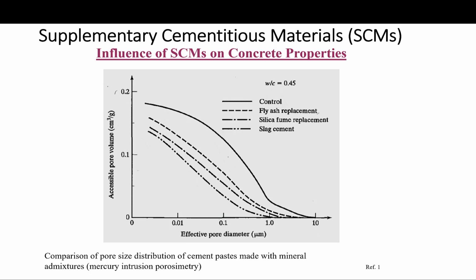The effect of mineral admixtures on pore size distributions is summarized in this figure - a familiar curve showing a comparison of the size distribution of a cement paste made with mineral admixtures, using mercury intrusion porosimetry. This is the accessible pore volume, and this is the effective pore diameter. You can see the reduction in the threshold pore diameter and the effective, or critical, pore diameter.